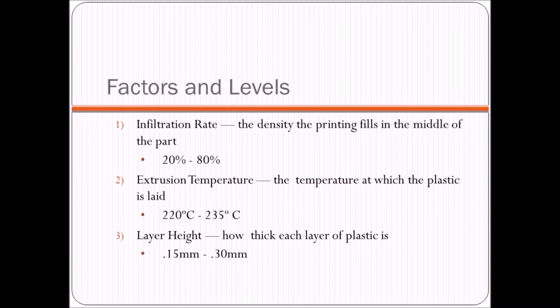The second factor was extrusion temperature. This is the temperature at which the plastic is laid. So if you think about a hot glue gun, you can think of this as the temperature of the nozzle that's melting the glue. Our bounds on this were between 220 and 235 Celsius, and we chose those because going lower than 220 degrees Celsius would basically jam up the printer. And 235 was on the upper spec limit of the printer's manual.